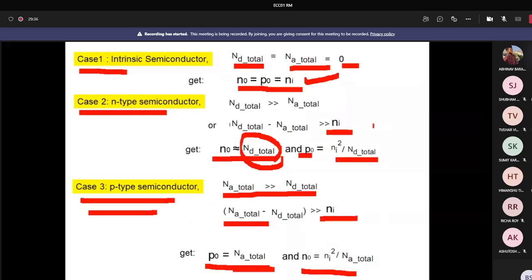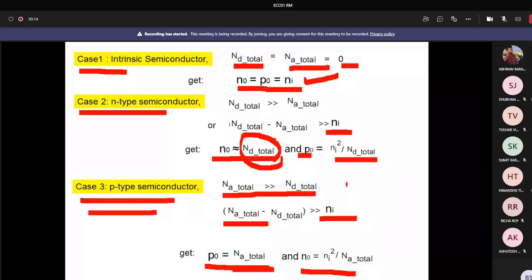Particularly for active devices, generally when we use silicon MOS devices or other devices, we use 10^15, 10^16 order carrier concentration, even 10^17 order. Whereas silicon intrinsic value is 10^10 order, we need 10^17, 18 or 19 order carrier concentrations. So for that you can increase the electron concentration value by your doping, either donor ions or acceptor ions.